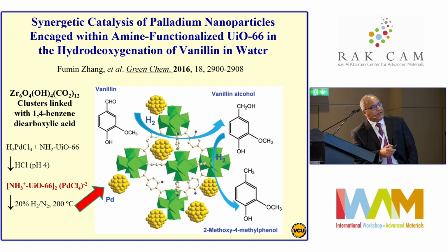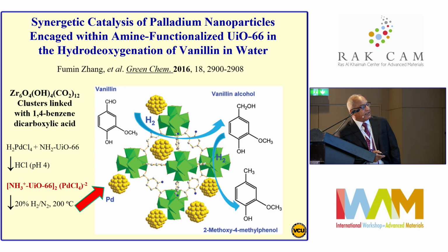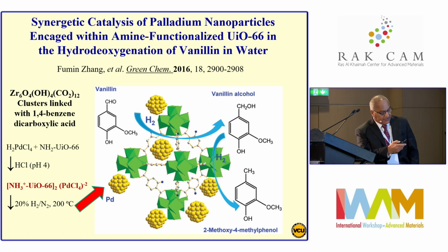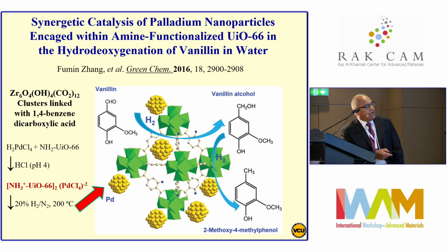The important point here of having the amine in the MOF is that when you incorporate the palladium, this happens in acidic conditions. So the formula that you will have is NH3+ UiO66 and the PdCl4 2-. So there is a strong electrostatic attraction here between the palladium ions, sorry, the palladium anion, and the amine complex. And this, following the reduction of the palladium ions, can ensure that you have well dispersed and very small palladium nanoparticles within this MOF.